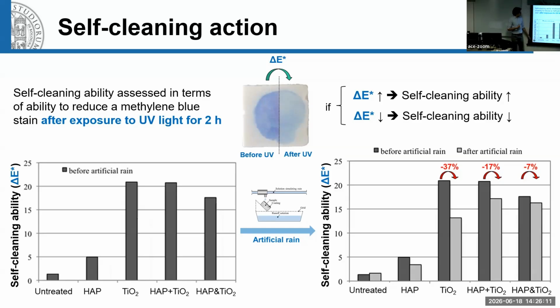So in these graphs here, you see that the untreated stone has basically no self-cleaning ability. If you use the titania alone, it has the highest self-cleaning ability. When you combine it with hydroxyapatite, you obtain some good ability. As I mentioned, the real problem is what happens once the surface is exposed to rain. So we did it in the lab, some accelerated aging. What we found was that titania alone loses most of its ability because, again, the nanoparticles are leached away. If you combine the nanoparticles with the hydroxyapatite coatings, you see here, you finally have a residual self-cleaning ability that is much higher, so you have a very reduced loss of efficacy because of exposure to rain. So you are able to provide the surface with a long-lasting self-cleaning ability.